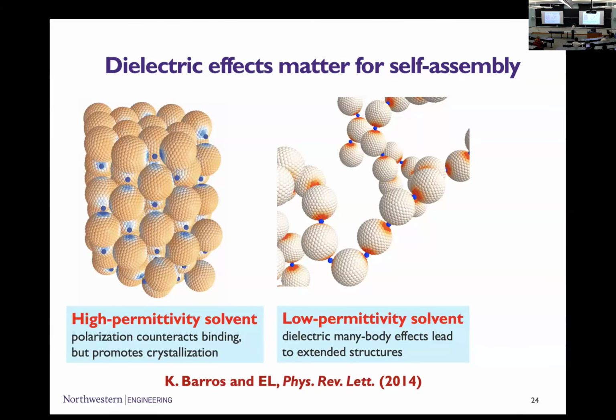The interesting thing here is that you say, wow, so you get a sodium chloride crystal structure. I could have told you this for positive and negative particles. It's less obvious than you may think. We all learn positive and negative from sodium chloride, because sodium and chloride have very similar sizes. Nobody tells you that. That's just taken for granted, and nobody thinks about whether, if the sizes are different, you would get the same thing. It turns out that the fact that we get the sodium chloride crystal structure here is surprising. It is due to the polarization effect. If I turn off the polarization effect, it would not form a sodium chloride crystal structure here. Something more like, I think, a wurtzite crystal structure instead.